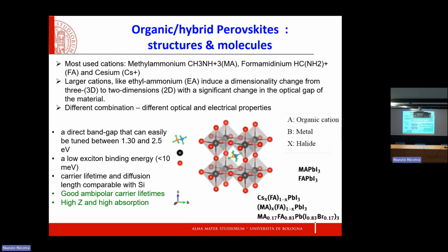Their gap can be varied, depending on the combination of components, between 1.3 and 2.5 electron volts. They also have a low exciton binding energy, and they have a very good carrier lifetime and mobility. So their transport properties are more comparable to the ones of silicon. They can also be deposited by solution, and they have, what is also very interesting, a very good ambipolar behavior that can be exploited. What is interesting for our application, the one I'm going to talk about today, are the good mobility and the high atomic number that induces a very good absorption of ionizing radiation.